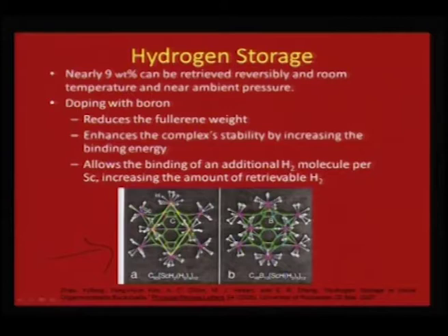You can see here a scandium metal center which is able to bind a rich amount of molecular hydrogen species, and this can become reversible. So, we can put it in and take it back. Doping with boron becomes very important in this case. It enhances the complex stability by increasing the binding energy, and this allows the binding of an additional hydrogen molecule per scandium, increasing the amount of retrievable hydrogen. This is a paper found in Physical Review Letters